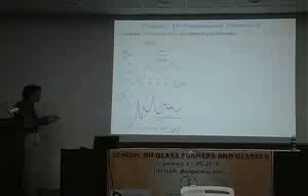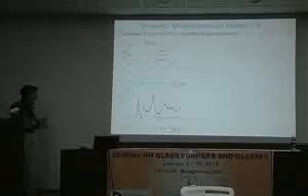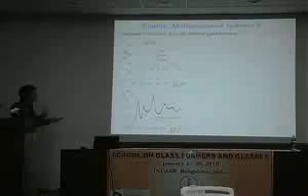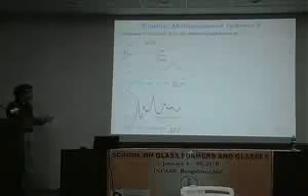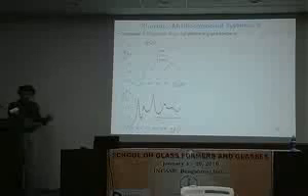So that's the truth. And then you let it run through this machinery, and the outcome is that this first peak here is more pronounced than the second peak here, okay? And it's just because you have taken this linear combination, and especially in the case of SiO2, the SiO static structure factor here, for example, is negative, and that's why this peak here is suppressed, okay?